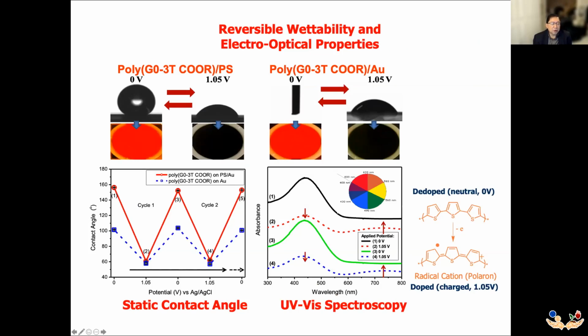Moreover, the transition from reduced to oxidized behavior is accompanied by color change. This color change makes it an electrochromic material or displays electrochromism. Moreover, the oxidized part is, as shown here, super hydrophobic, and the reduced part more wetting than ever. So the color orange or green allows us actually to visualize the wetting or non-wetting behavior of these films.